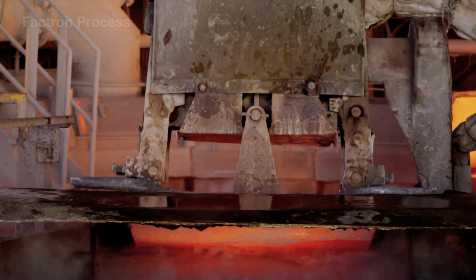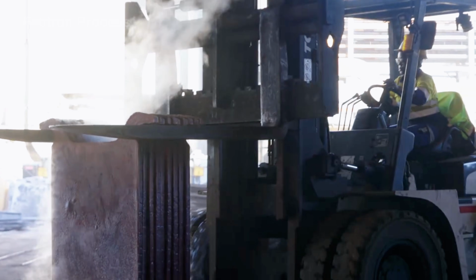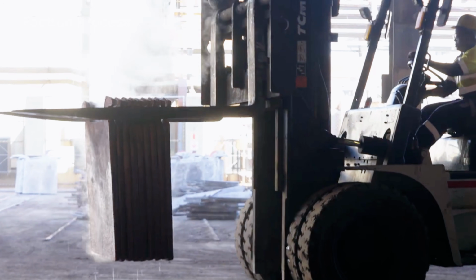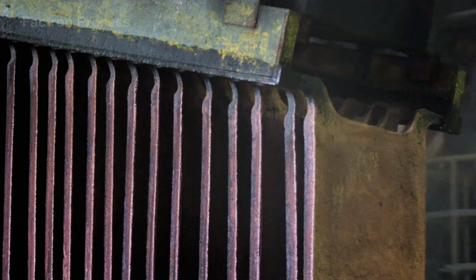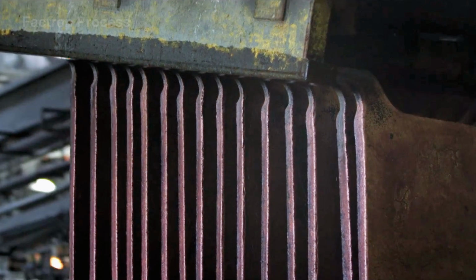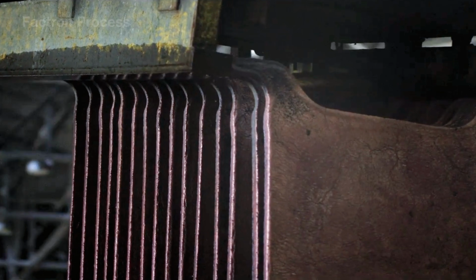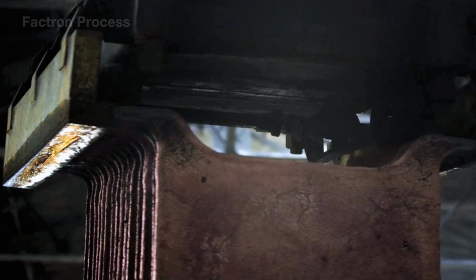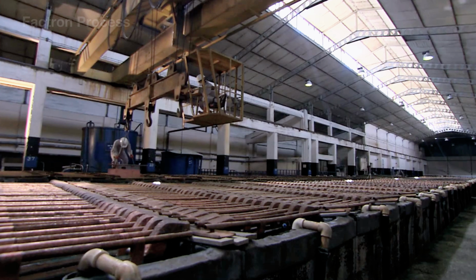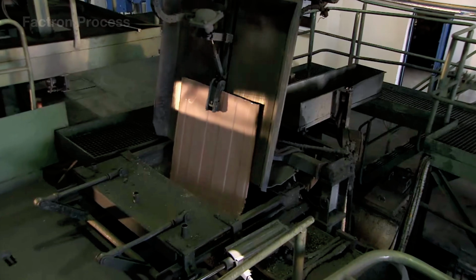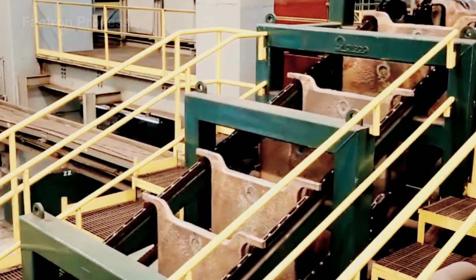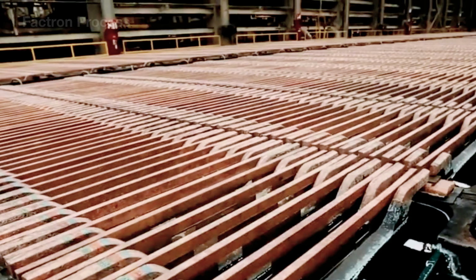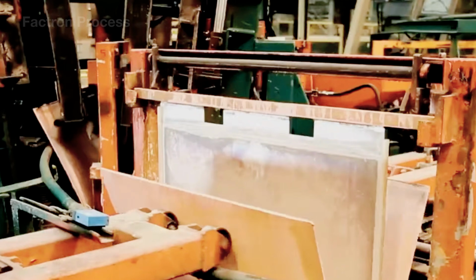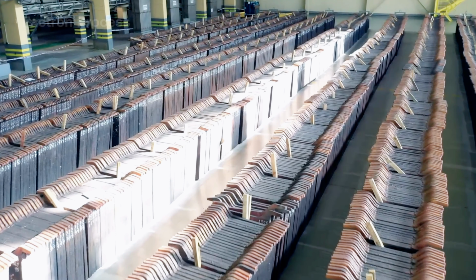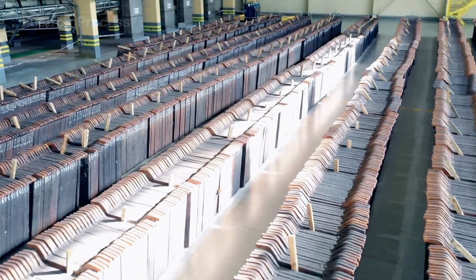After being cast into plates, the copper is lifted and transported to the electrolysis area for the final refining stage. Here, each copper plate is suspended inside enormous electrolytic tanks, alternating with thin metal sheets. When direct current is supplied to the system, copper from the crude copper plates begins to separate, dissolve into the solution, and gradually deposit onto the neighboring metal sheets. This process continues for around 7 to 10 days.